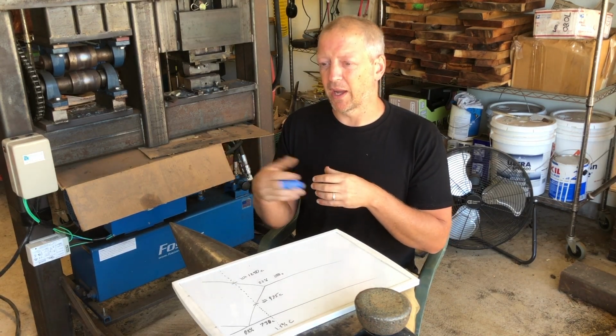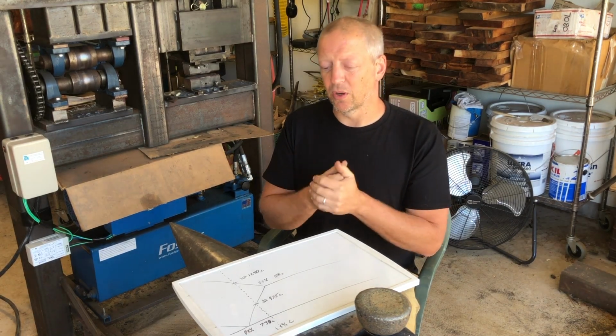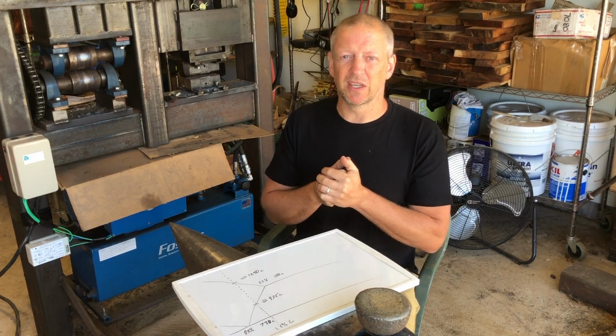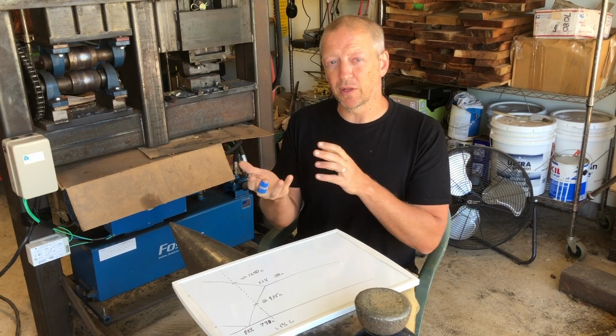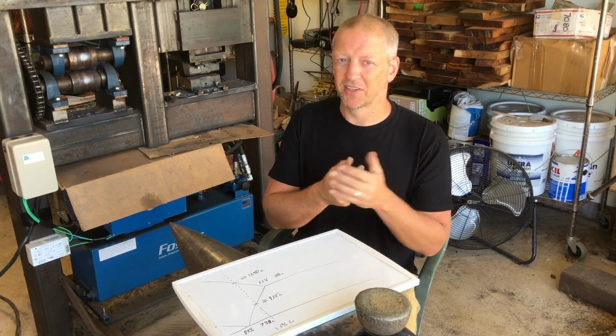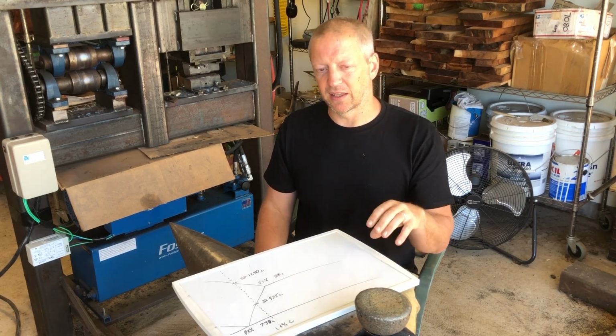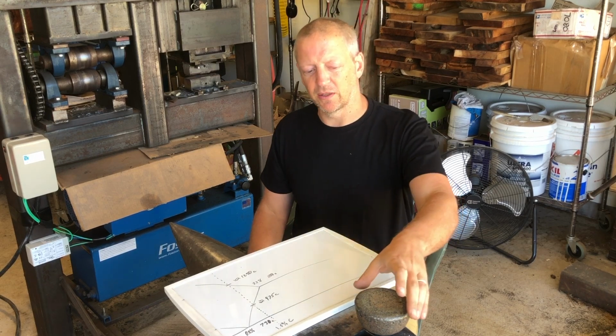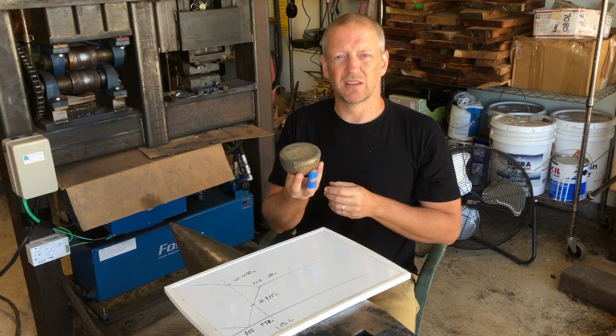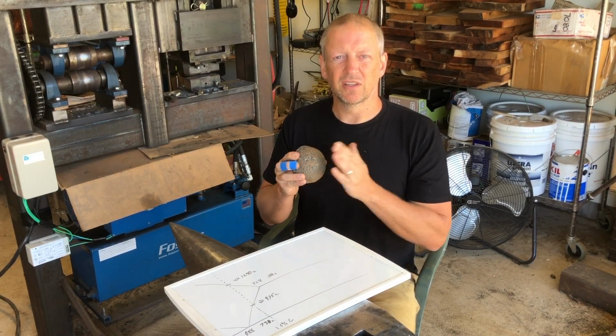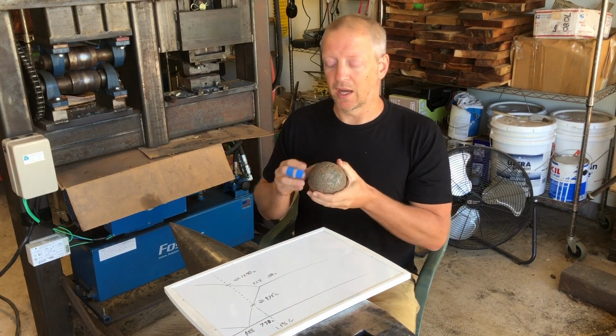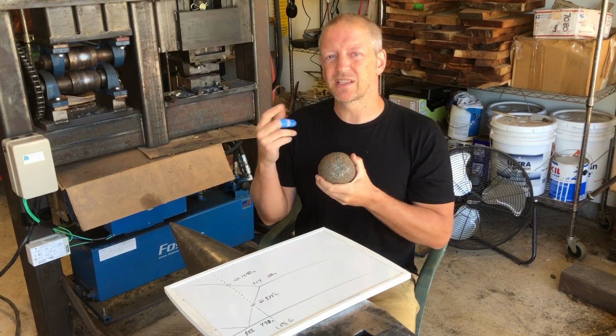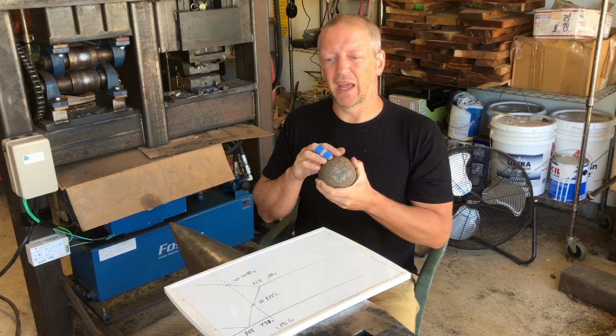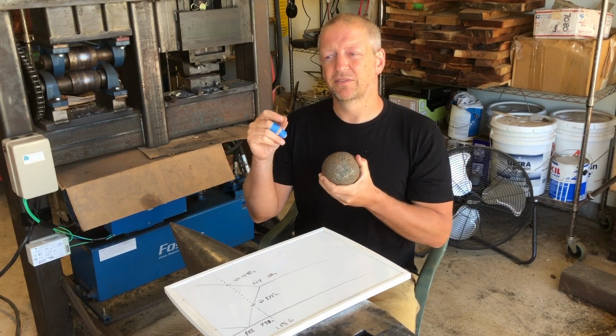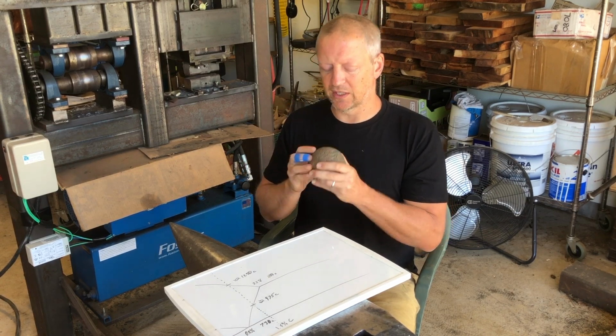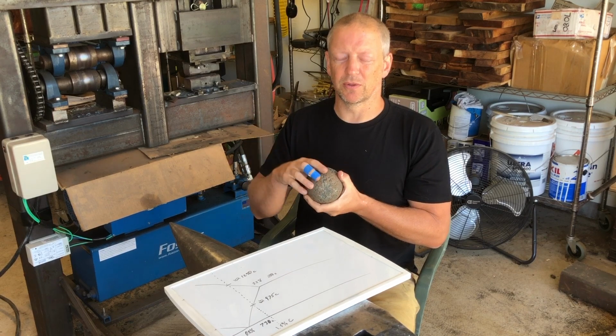This was also written by an observer rather than the smith, so that also adds in a little bit of murkiness. Was the observer being shown a real process or a fake process? Hard to know. But in either case, the idea that they were going with, apparently, was they would heat and roast the ingot in the forge for a while, bring it out, put it on the anvil, give it a tap, hit it, obviously not with your hand, hit it with a hammer, get an idea what it sounded like, what it felt like, and then the smith would evaluate, did this feel or sound ready to forge? Was the ingot good to go? If not, back to the forge, keep going through that process.